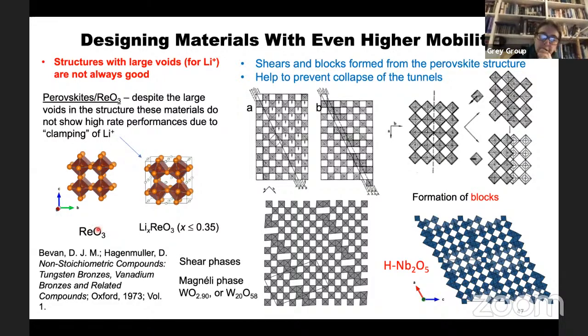And so I'm not proposing that you make a rhenium trioxide battery. I'm just literally using this to illustrate the structural issues. And so the solution is to think about how you stabilize these open structures to stop that happening. And nature does that in a number of different ways. You can have these shear structures, for example in TiO2 when you reduce it, where you get a shearing of these blocks to form these octahedra. So this square is looking down an octahedra, and you can see, instead of it being corner-shared octahedra, it's edge-shared after the shear. And what that does is it gives more